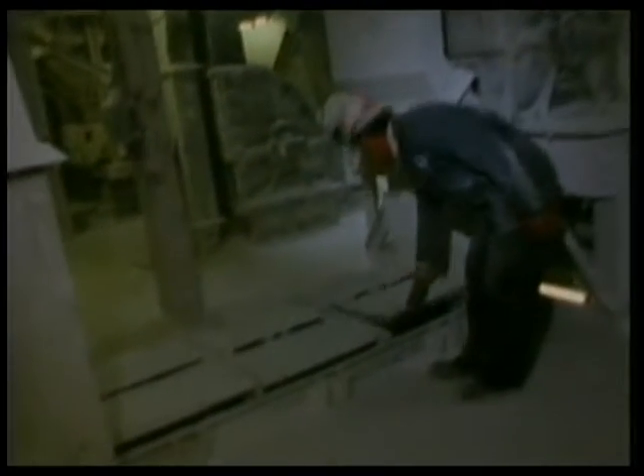It's a continuous process, and the water goes in here, mixing with a thin stream of quicklime driven along by a screw. The quicklime water mixture is driven along through a series of cylinders, and when it gets to the bottom, all the quicklime has been turned into slaked lime, calcium hydroxide. There are several sets of these hydrators. By gradually mixing the quicklime with the water in this way, a smooth, controlled reaction is achieved.